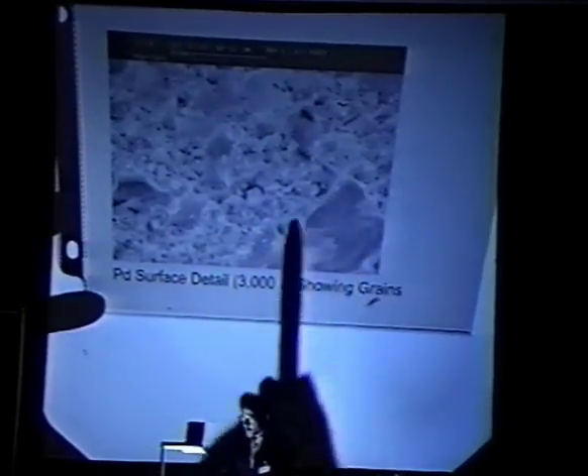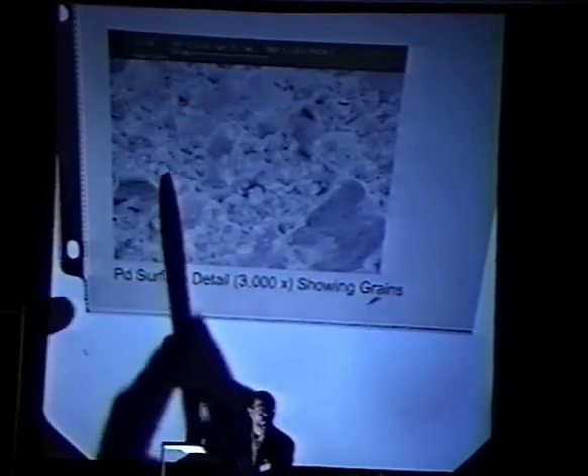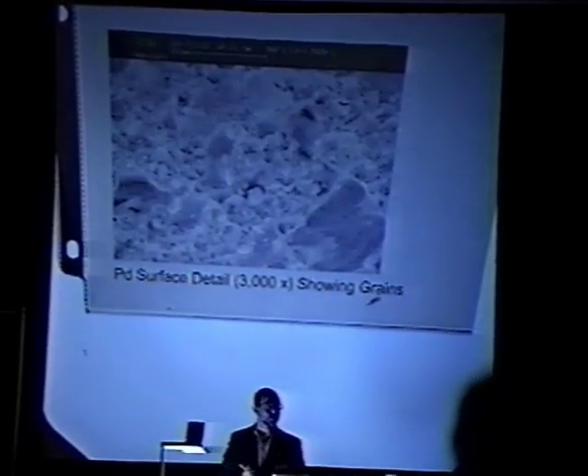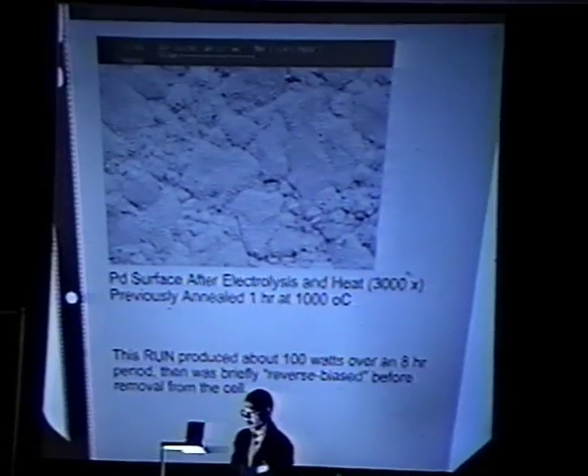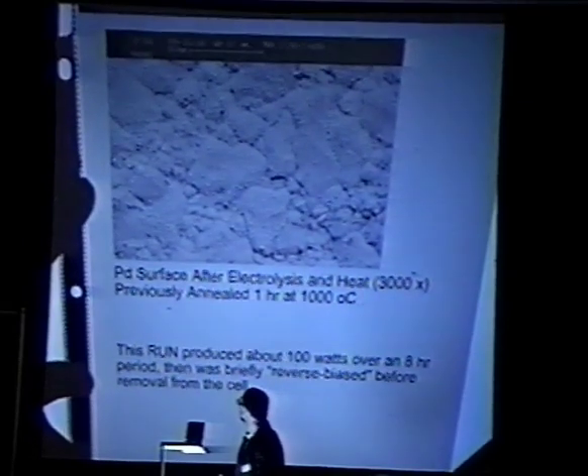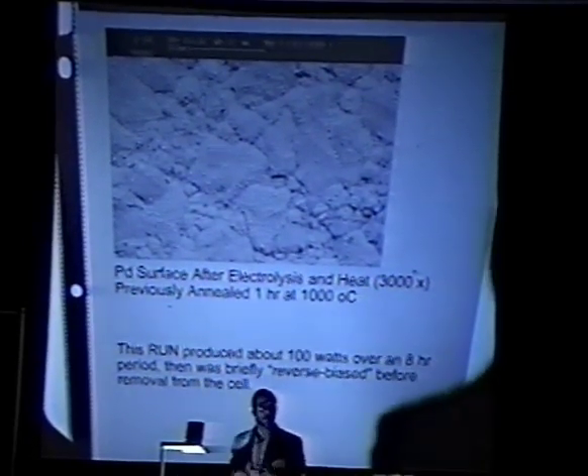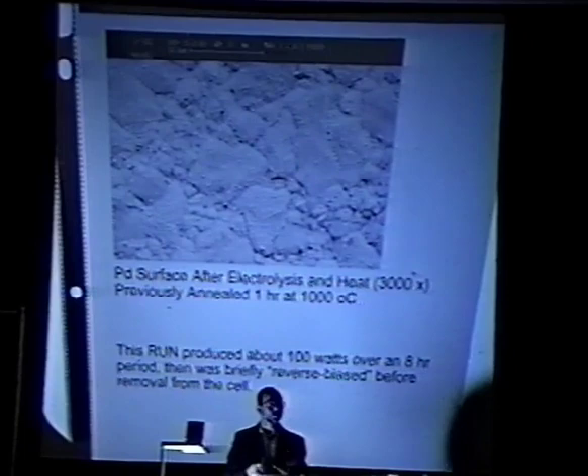We see several large grains growing and again smaller ones, but this is just real typical of annealed polycrystalline materials. So I tried both of those in the system to see if there was any difference. And here's one with the annealed coating after electrolysis. And what you see are some of the same types of things we saw on those that were as deposited.